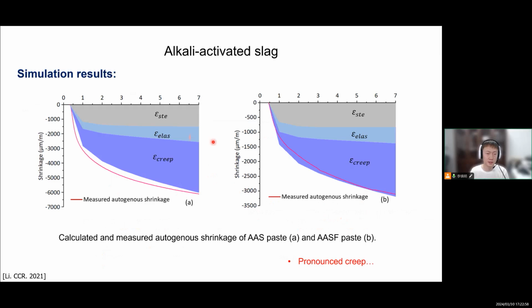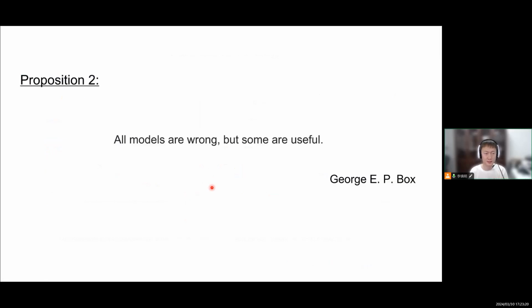So this is the simulation result. We can see that indeed it matches really well with the experimental data. So there are three parts: steric hydration force, elastic part, and creep part. Actually, a very big creep part. So which means that our understanding of the mechanism should be right. So as a famous professor said, all models are wrong. Actually, these models are also not right.